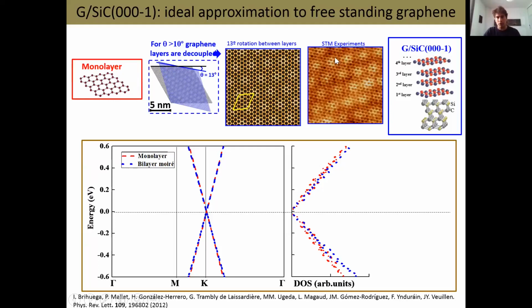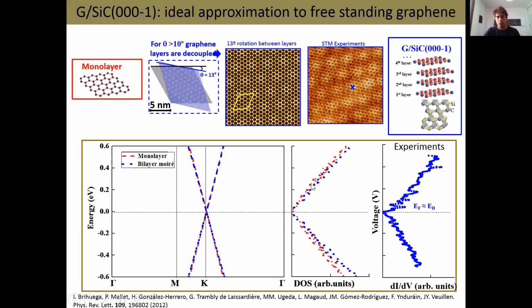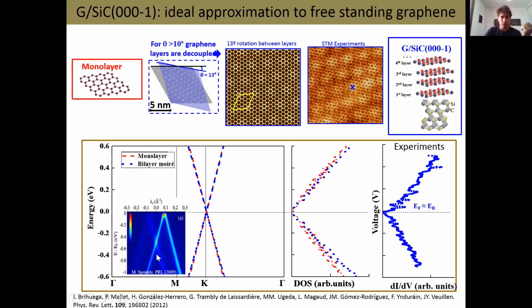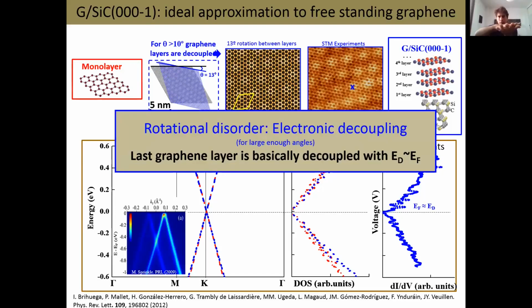And with STM, you can measure the Moiré periodicity. With this, you can know the angle. This is an experiment measured on a graphene layer which is rotated 13 degrees. And then if we measure the dI/dV, we can see that really we recover the properties of freestanding graphene with the Dirac point at the Fermi level. And of course, this has also been measured by other techniques such as photoemission. We see here the very nice linear bands that you get on this system. So the message we have to get here is that if you have two graphene layers which are rotated more than 10 degrees, this is a very good approximation to, let's say, ideal graphene. And that's the starting point of almost all the experiments that I will be showing today.